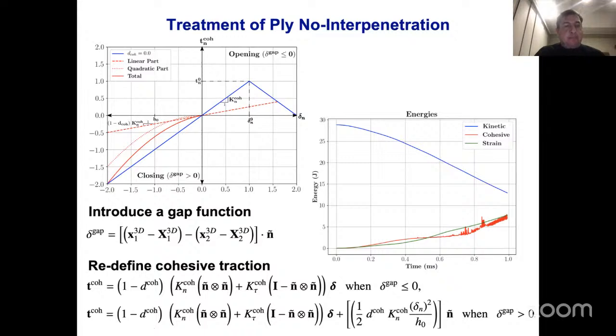By basically taking the original cohesive stiffness, through a cohesive variable, we're letting it go to 0. So eventually the slope here becomes 0, but then we add a quadratic sort of penalty that's proportional to the amount of damage that's been developed. And you pick up a curve with a 0 slope that comes into the origin here.